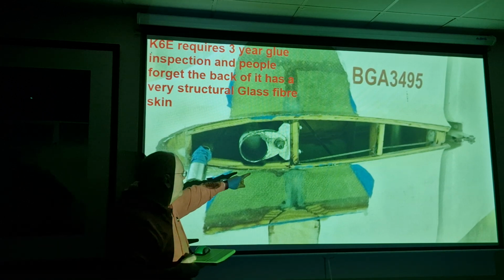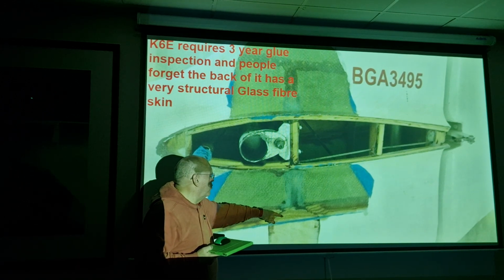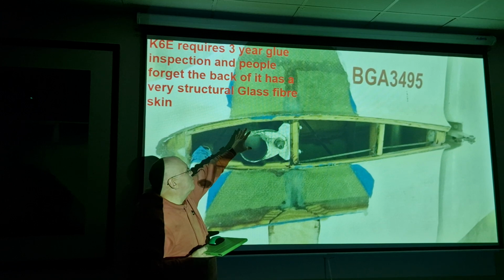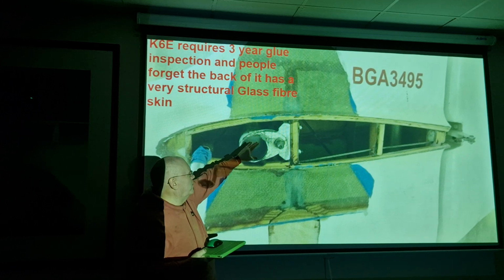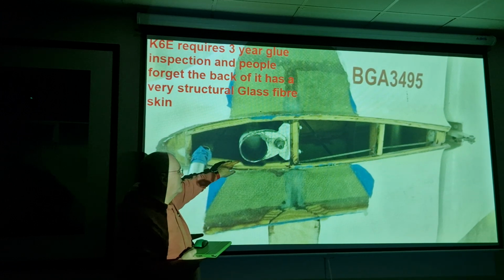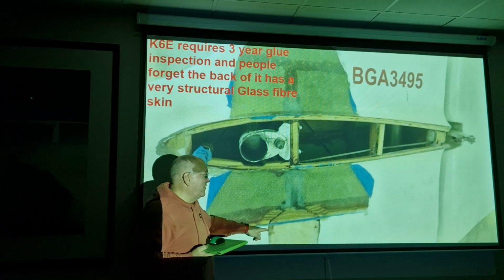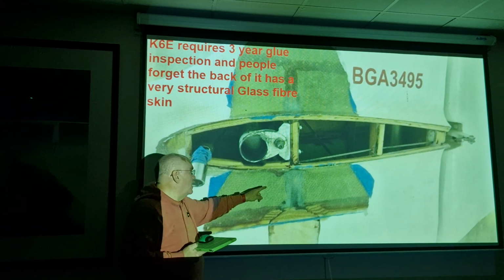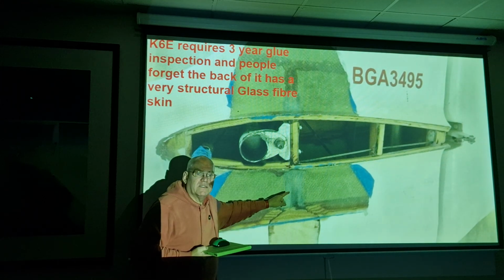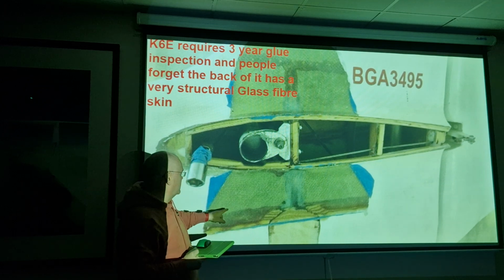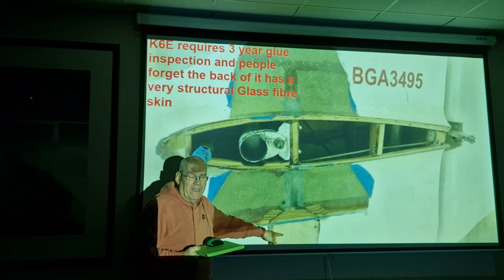What happened was it unbonded the glass fibre and the wood frame there, but it didn't actually damage anything, it just wasn't stuck together. You couldn't just glue it back together, it was impossible to get in there. So what we had to do was take the wood off, do a 15-to-1 splice, take the glass fibre off, and do a 40-to-1 splice, and that's why you can see the glass fibre repair is much bigger than the wood repair.